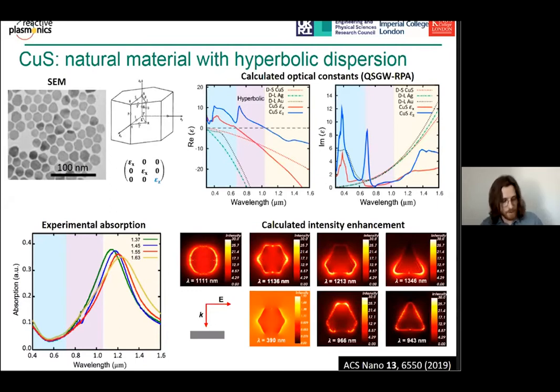And these materials, the nanocrystals, have different efficient hot electron ejection and generation possibilities, because they have high field enhancements at different locations based on the shape of the crystal. So we can potentially use these to generate hot electrons from these high field areas.